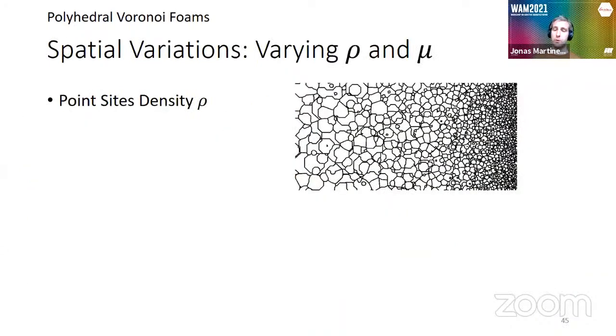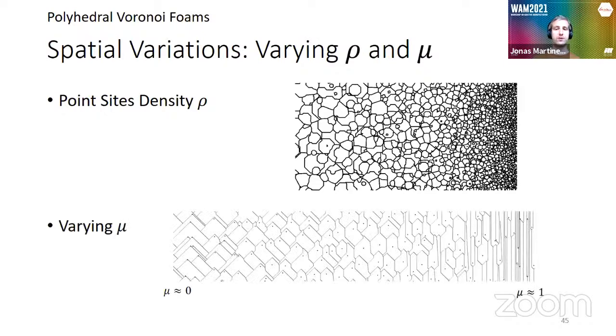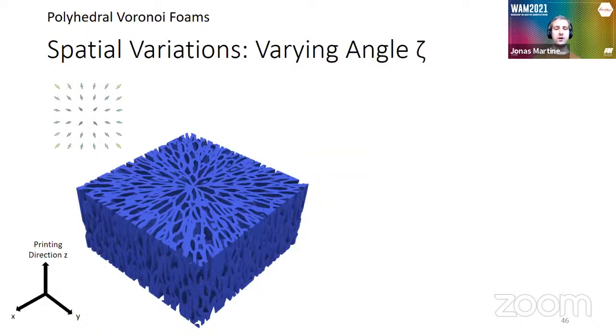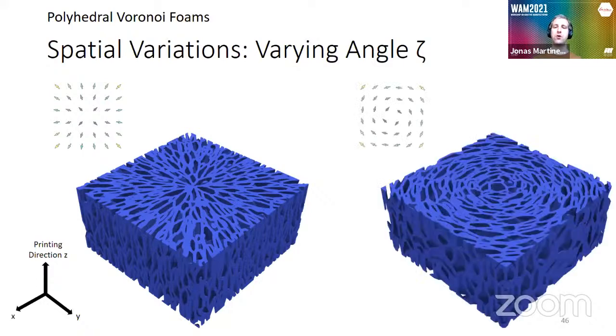So what can we do? Always keeping in mind that we can do these gradations implicitly just by changing the parameters, as opposed to periodic tilings. We can change the site density of the points that generate the Voronoi diagram. We can also, for instance, here vary smoothly the parameter mu that controls from non-vertical to almost vertical. And here we can do even more interesting things. So here we have a concentric field of direction, and we can guide the distance with this field. So you can see that you can have materials that are concentric or orthogonal to the concentric field. You can provide any arbitrary field as long as it's defined per slice.